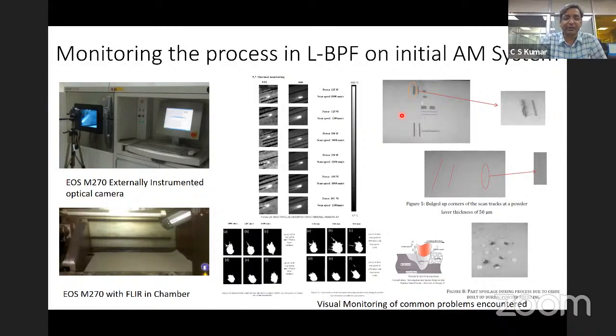There are snapshots that we take through a thermal camera, and we can detect from that what is happening in the process. Sometimes it does not go well as planned, and it may introduce defects. So we look at defects by looking at the intensity of the laser energy, which varies with the various process parameters that we change, or the spatter, which shows how high the plume is, and whether it is ejecting too many particles, or is likely to create more errors in the job. Like there may be pores, or there may be lack of fusion faults that may happen. So we need to capture them early.